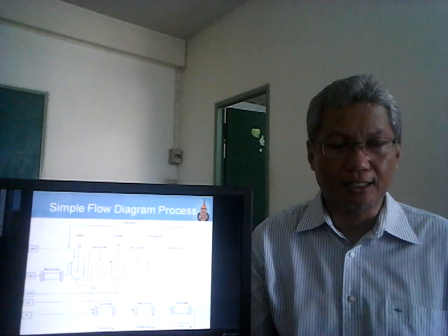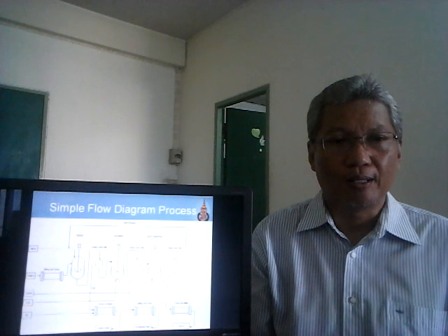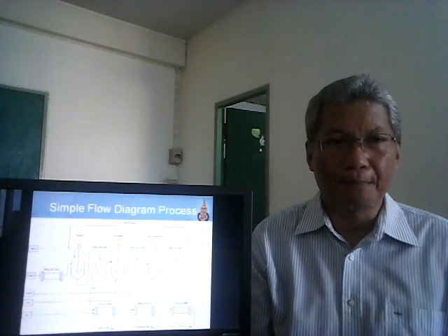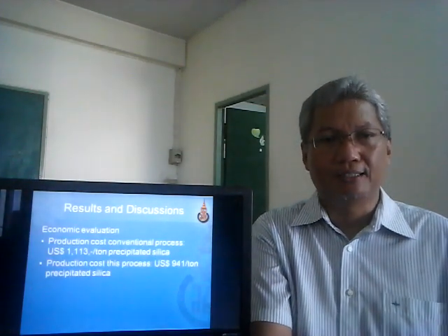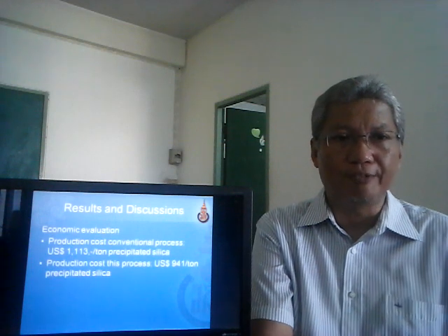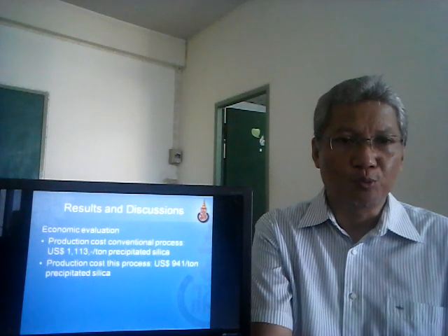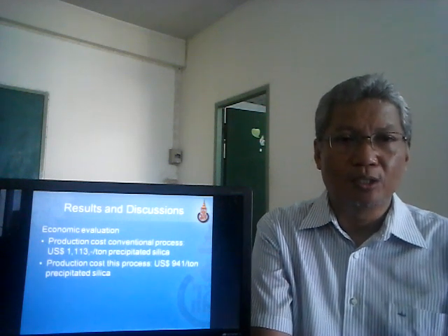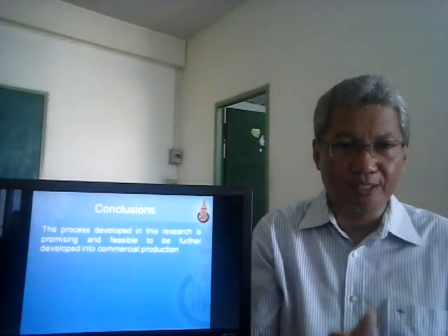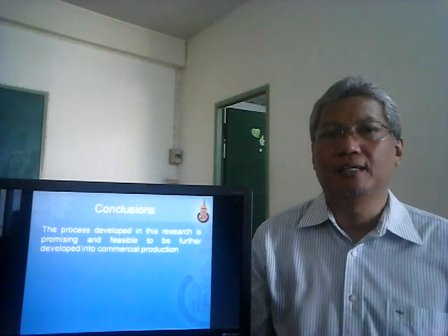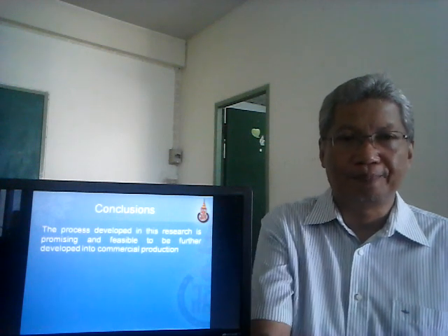Based on the result of my research, I can develop a process for silica production from palm oil mill fly ash. Based on this process, I made an economic evaluation, and the result is that the production cost of this process is lower compared to the conventional process. So the conclusion, the process developed in this research is promising and feasible to further develop into commercial production.